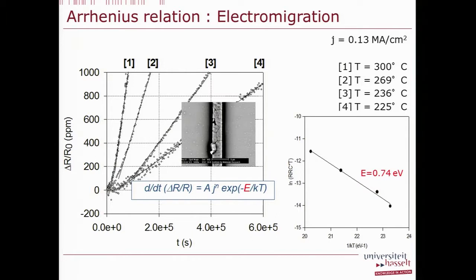Electromigration is a degradation that occurs in thin metal lines that you have in your computer. Since they are very small, if you send current through it, you have a very high current density, and that can really blow away metal from one side to the other. This effect leads to a change of resistance, and you can see here the rate of resistance change is very small, 1000 ppm, so very small changes. If you want to see this in an accelerated aged manner, you really have to go to very high temperatures. These measurements shown here are measured at temperatures up to 300 degrees Celsius.